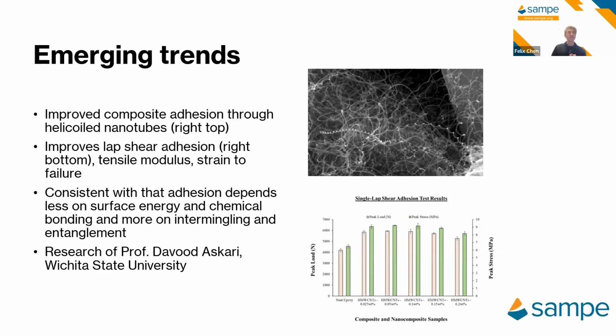Another thing I want to point out is that the adhesion here depends hugely on entanglement and intermingling. That goes against the conventional wisdom that there's a lot of a role played by surface energy and chemical bonding. If you've ever seen the work of Professor Kevin Kendall, he did a lot of this work in the 70s, but he has debunked a lot of the usual guidelines about increasing surface roughness and surface energy, and focuses more on the entanglement. This work with Professor Davood Askari goes hand in hand with that. And some of the presentations I've seen in previous conferences also support this type of work. The next slide.